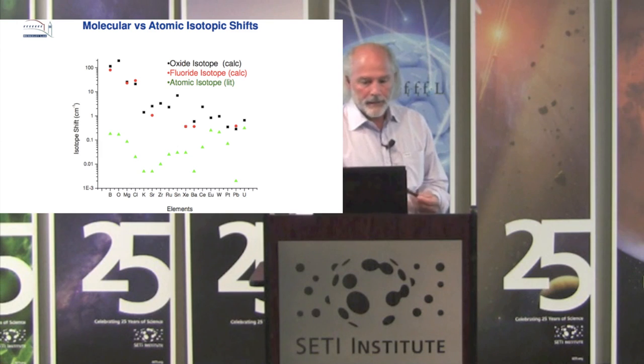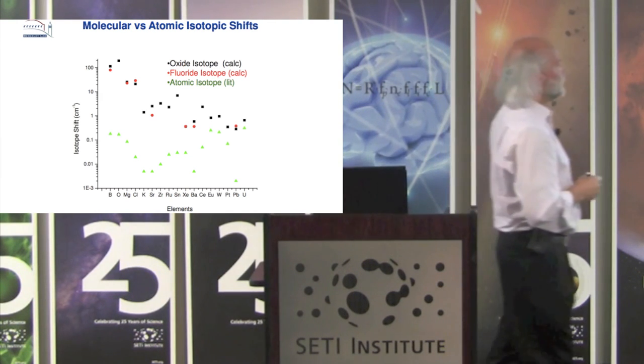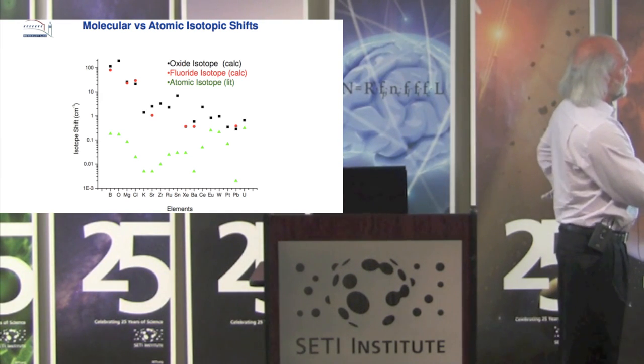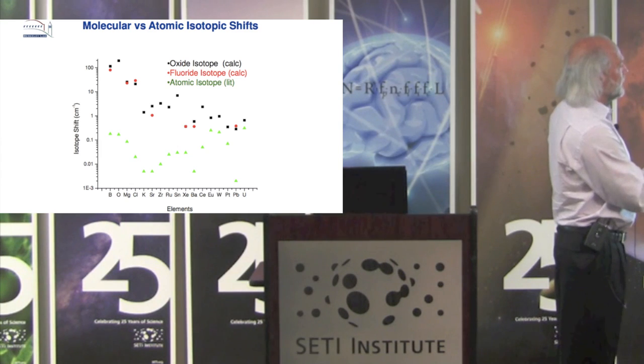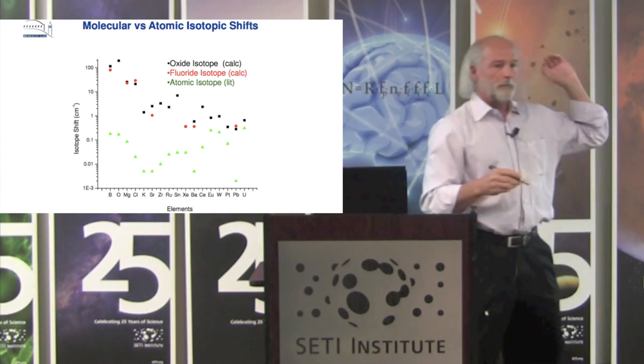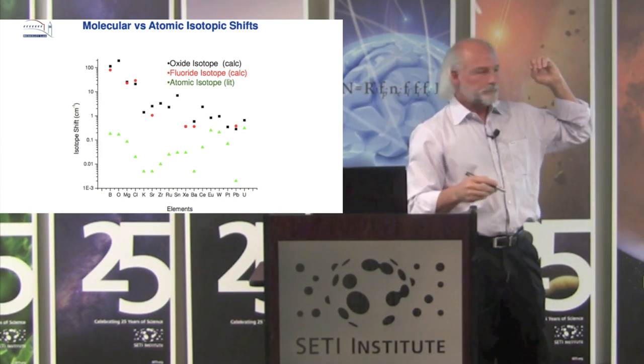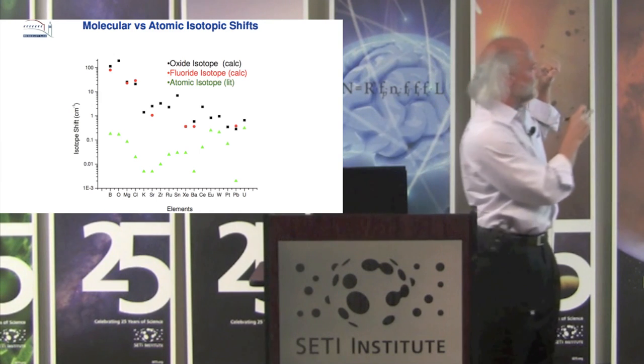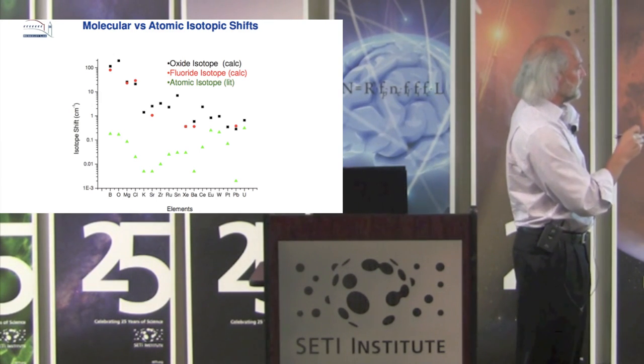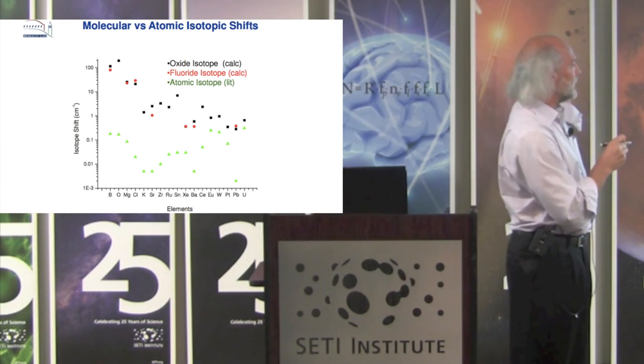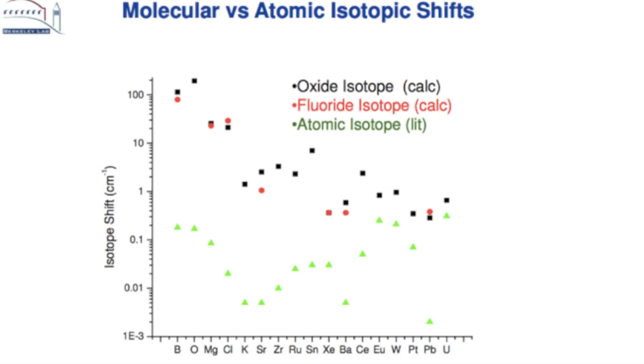So I know I'm beating heck out of that. But this is sort of the summary slide. We did a calculation. These data are the same as that one I showed you from the Livermore program, where we just transposed their data onto our curve, and instead of calling it mass number, we actually listed the elements. And again, we plotted the shifts in wave numbers, because just like that strontium, it depends on where you are, what the shift will be.